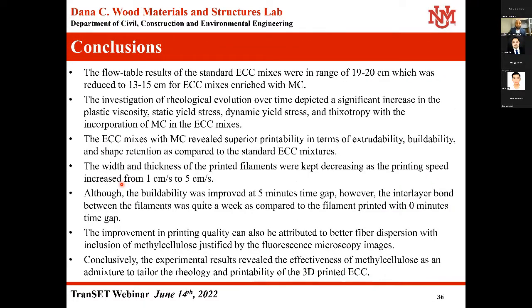In the end, the methyl cellulose was a quite effective rheology modifier, and it helps in improvement of the fiber dispersion in the mix that ultimately helps in improvement of rheological properties such as plastic viscosity, yield stress, and thixotropy.